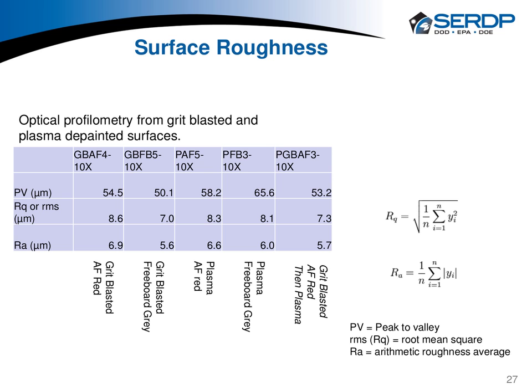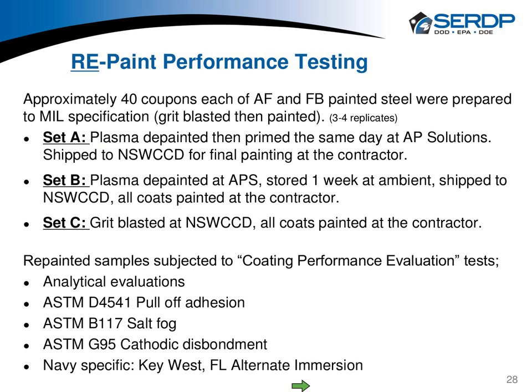So to back up that data, we did optical profilometry, and here's the result over a number of different samples, whether they were plasma, freeboard, anti-fouling, grit blasted. We even took some of those grit blasted samples and then plasma treated them to effect removal of the rest of the paint. In all of the cases, the profiles were around 50 microns, which makes sense. It's not on this slide, but the grit that was used was a 5 mil grit intended to achieve a surface profile of 2 mils in terms of roughness, and that's 50 microns. So this gives us a couple of really interesting data points. One, all of these surfaces had roughly the same type of roughness, and two, the profile is what is desirable for the military application. All right, so we moved on.